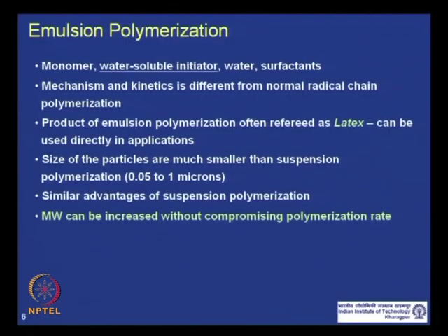Now, in case of emulsion polymerization, you have apparently similar composition: monomer, water as a medium, surfactants as a dispersant, but the only difference in this case is that you have a water soluble initiator. In suspension you have monomer soluble initiator; here you have water soluble initiator. Now, apparently it looks like a small difference, but this has very far reaching implications in terms of the mechanism and the kinetics of the polymerization process in emulsion.